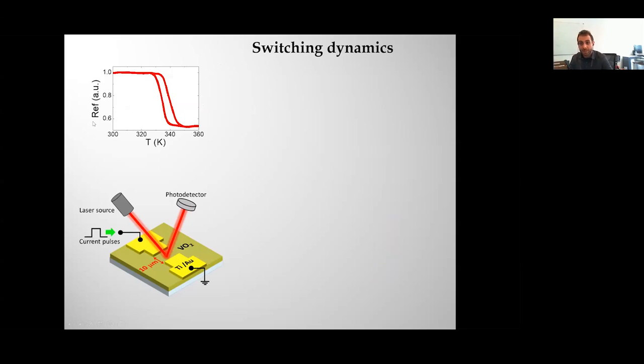So it turns out that reflectivity is a great proxy for that. This is reflectivity in VO2 as a function of temperature. And you can see that it gives you a really good contrast between the insulating and the metallic state. You can see the hysteresis of the transition and everything. So it is a very good indication of how much metallic domains you have